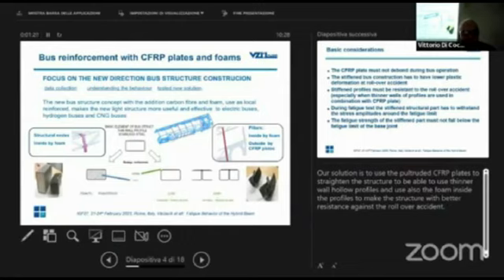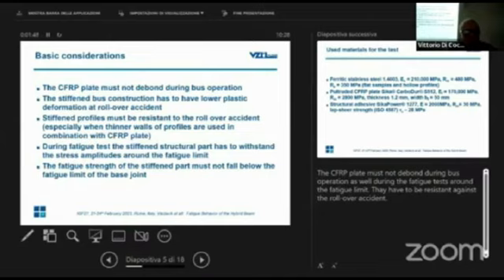So use the CFRP plates which are glued on the structure on the hollow beams, and also to fill these hollow beams with some foams. But the basic consideration to solve this is that this CFRP plates must not be debonded during the operation of the bus, because still